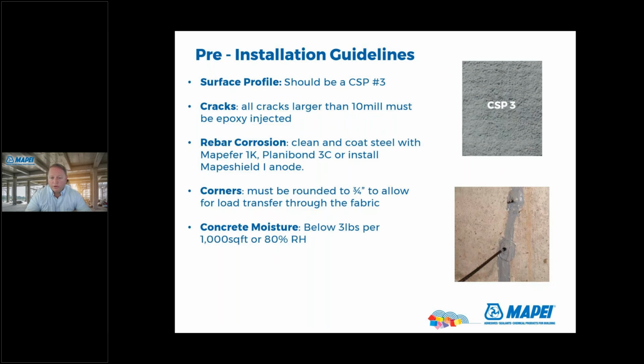The concrete moisture, you want this to be below 3 pounds per 1,000 square feet or 80% relative humidity. And then the installation temperature between 40 degrees and 90 degrees. So in some projects where it's much colder than that, or they're doing it in the winter, they'll tarp off the area and they'll add external heat sources.